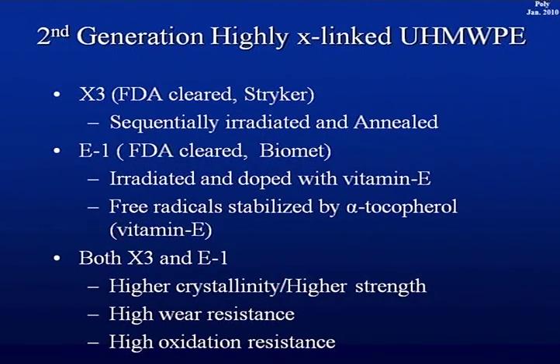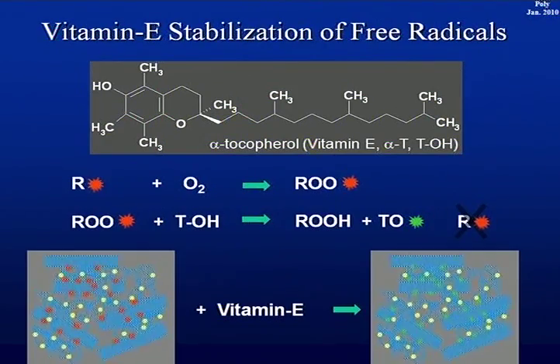And the other alternative is, you remember the red dots. If you block the red dots with an antioxidant, then it won't oxidize the material. And you can do that by somehow getting vitamin E into the material. And both these 2 have higher crystallinity, higher strength, high wear resistance, and very high oxidation resistance.